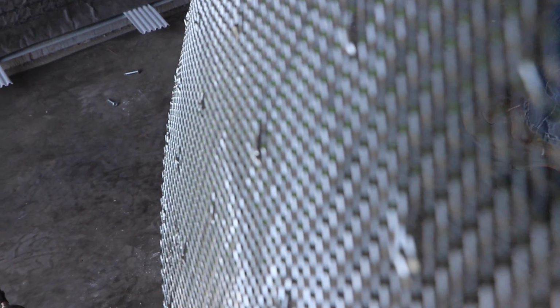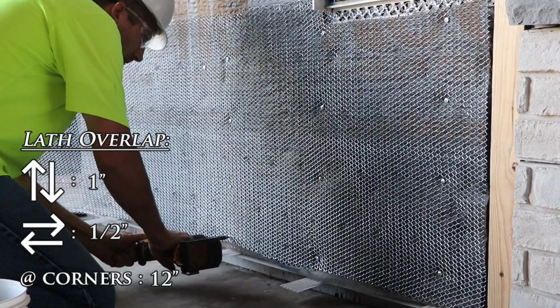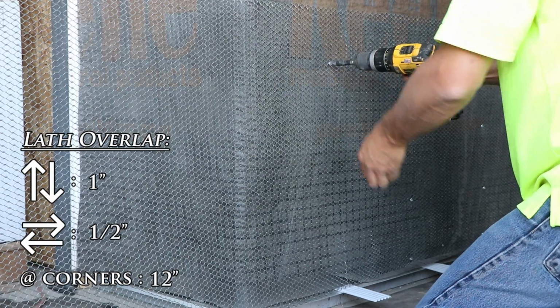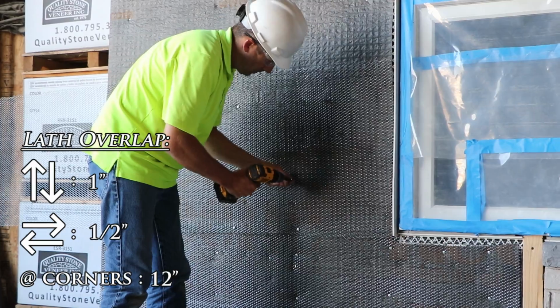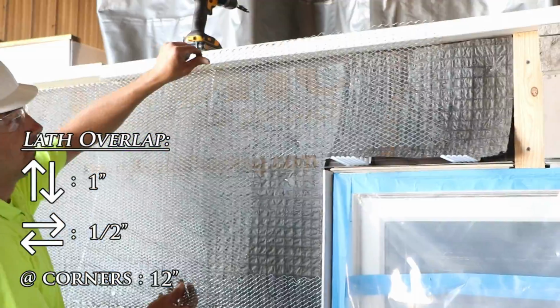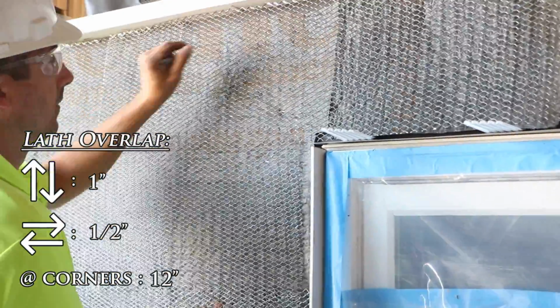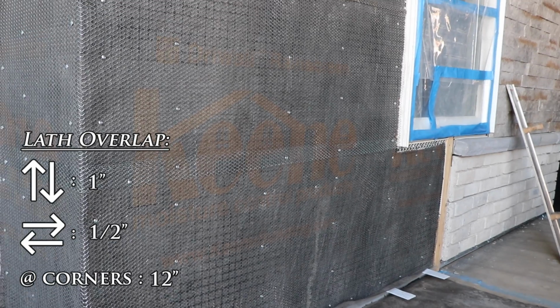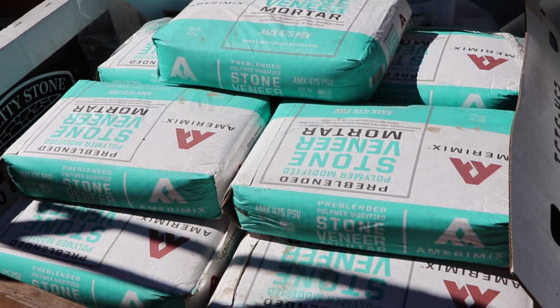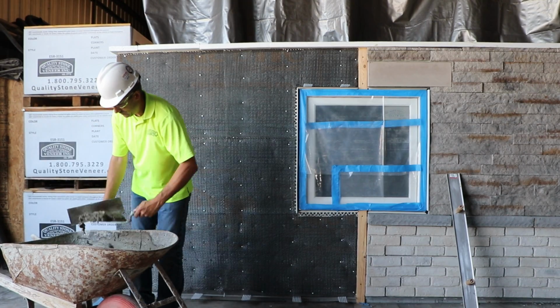Install the wire lath next, with the dimples in the lath facing towards the wall. Per the NCMA, lath should overlap a minimum of 1 inch at the vertical seams and 1/2 inch at horizontal seams, wrapping around inside and outside corners a minimum of 12 inches. Finally, we'll add our mortar scratch coat using a polymer modified mortar for improved bond strength and curing. Use a generous amount of mortar covering the lath completely.